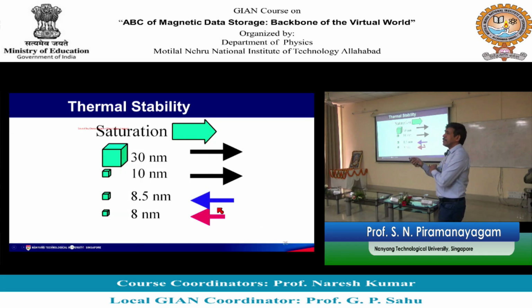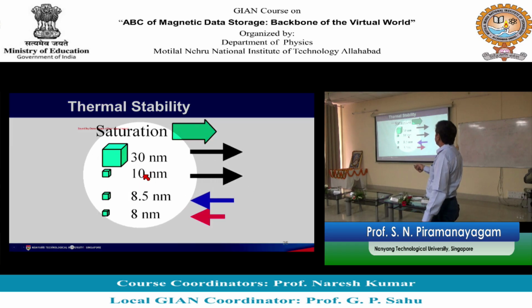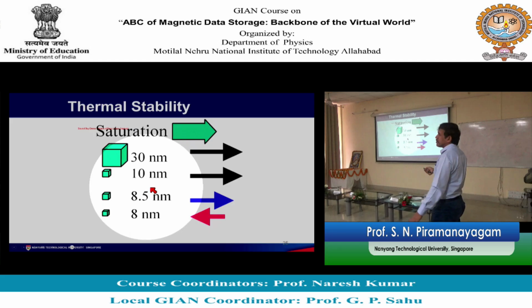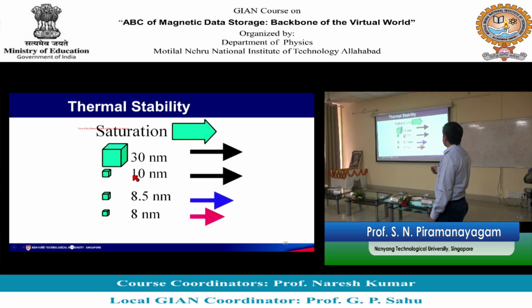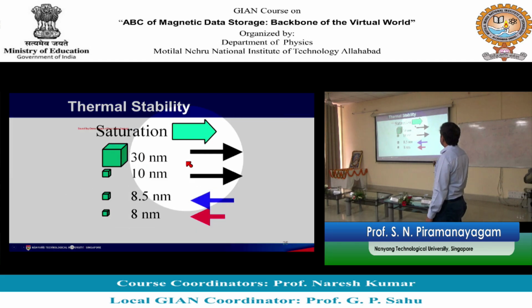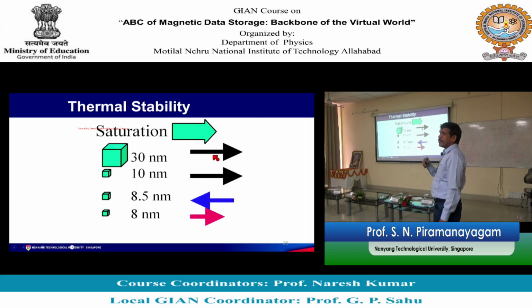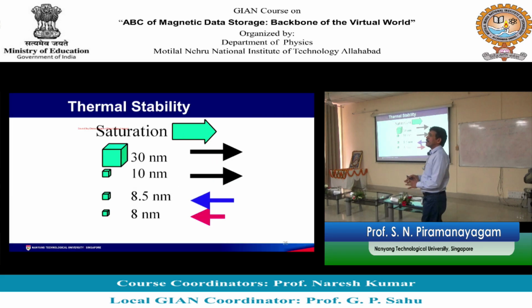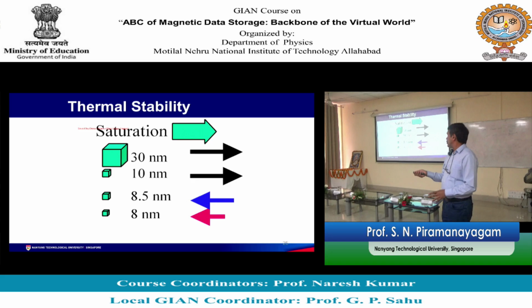So, what is happening here is that the magnetization is not stable. We are not doing anything, we are just keeping this at room temperature and just observing. There is no magnetic field. After we saturate the magnetization along this direction, we have removed the magnetic field, and we are just observing the magnetization, but the magnetization keeps fluctuating as a function of time.